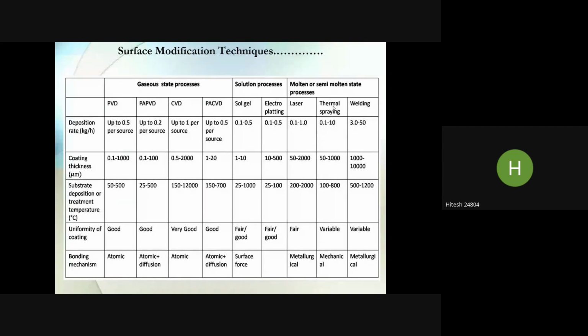You can see the deposition rate in kilogram per hour is very high, up to 10. Then coating thickness, look at this. This coating thickness is in microns. The maximum thickness is in case of welding. Why welding? Because claddings are there, so you can deposit a cladding also. Dr. Gurpage is also working on microwave cladding, so he is capable of producing a layer of 2 mm, 3 mm. But in case of thermal spraying, we deposit a layer of, let us say, 500 microns at max.